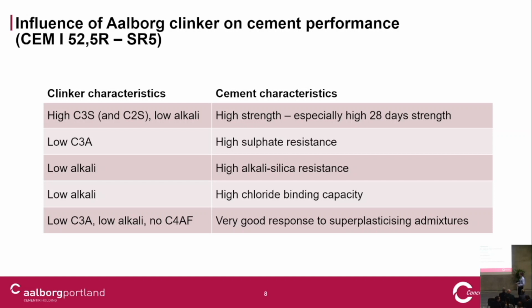That gives high strengths. The white cement on this clinker has more than 70 megapascals usually in 28-day strengths, and that's higher than almost every other cement.